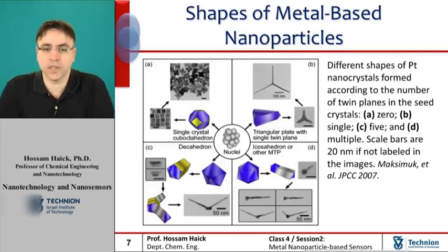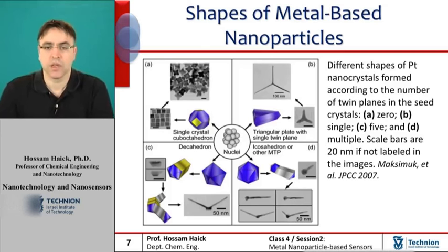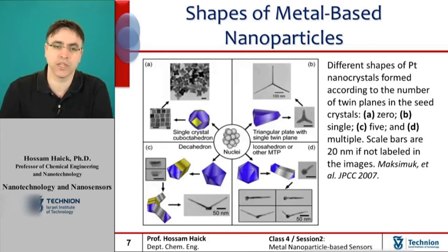Facets that are less energetically stable have higher motivation to keep growing and adding new atoms to them than the others. Therefore, by controlling the reaction conditions, more metal ions are added to the specific unstable places on the nanoparticle surface, thus resulting in larger particles of particular morphologies or habits. Typically, the growth stage is much slower and proceeds under milder reducing conditions than the nucleation stage.